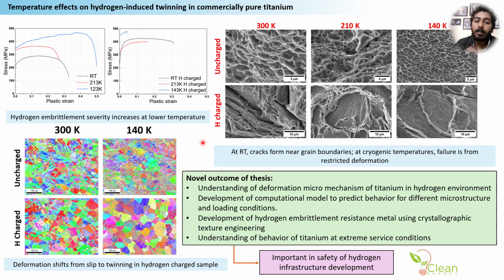So the novel outcome of this thesis is, first, that we developed an understanding of the deformation micromechanism of titanium in a hydrogen environment, and the second is the development of computational models so that we can predict for different microstructure and loading conditions. And then we developed a hydrogen embrittlement resistant metal using crystallographic texture engineering. And lastly, to understand the behavior at extreme conditions, we also performed cryogenic testing, which is important for the development of safety in hydrogen infrastructure.